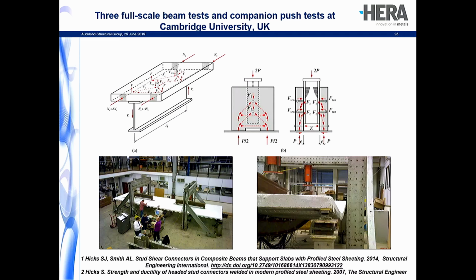And you probably recognise the picture from the invitation to this evening's presentation. This involved 3 full-scale beam tests. This was done at the University of Cambridge. And two of the things of note here is that the reason we did these tests was that one of the things that is absent in a push test is that you don't normally have a normal force applied to the face of the concrete slabs. Whereas if we have a beam test on the left-hand side, you would obviously have the weight from the self-weight of the slab plus the uniform distributed load from the working conditions. So this was one difference in those 2 specimens.